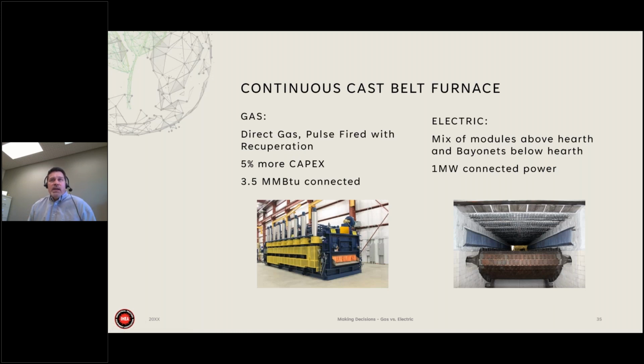This type of furnace is a belt furnace. It could be a mesh belt, or in this case, a cast belt furnace. Cast belts offer heavier loading. The gas type here was a direct fired with pulse fire and recuperation. It cost 5% more, not much of a penalty or savings going either way here. And the connected heat input for the process and production volume was 3.5 million BTUs connected. The electric option here employed a mix of both the modular rod overbend type heating elements you can see above the hearth, and below the hearth we actually used bayonet inside of radiant tubes to help with the mechanical damage below of anything falling down from scale or the like. And it had a connected power of 1 megawatt. So you have to make sure that you have enough facilities power from your utility company when you're going to be looking at installing this. It adds up quickly.